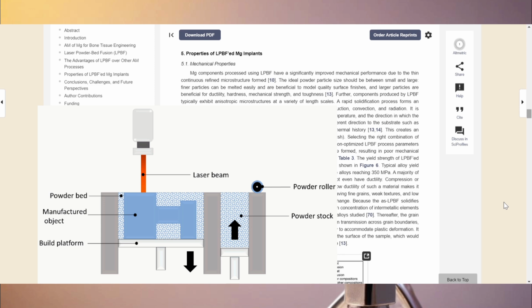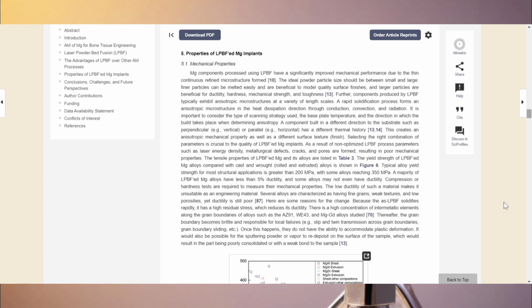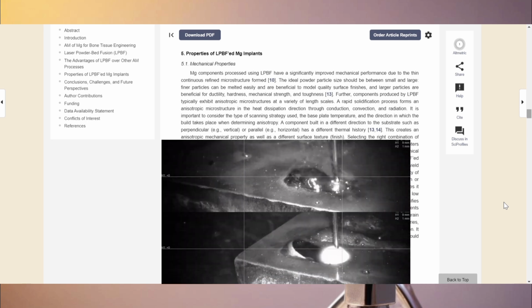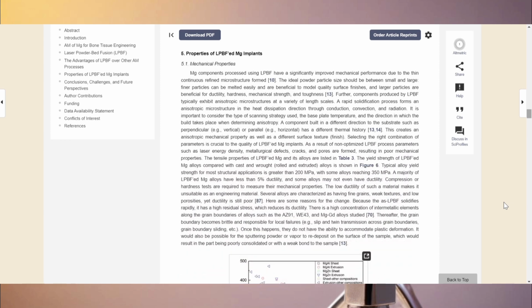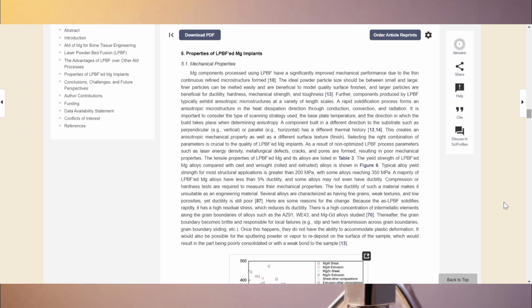Compared to electron beam powder bed fusion, LPBF's smaller spot size and powder particles let you stick more closely to your original digital design. There's also wire arc additive manufacturing. While it's great for certain applications, it can leave metal scaffolds too coarse for medical use, and its wire feed limits your alloy options. Plus, parts made via wire arc can have rough surfaces and higher degradation rates inside the body. Altogether, LPBF's ability to build near-net shape parts with intricate features and minimal material defects makes it especially appealing for creating magnesium implants that need to be both strong and biocompatible.